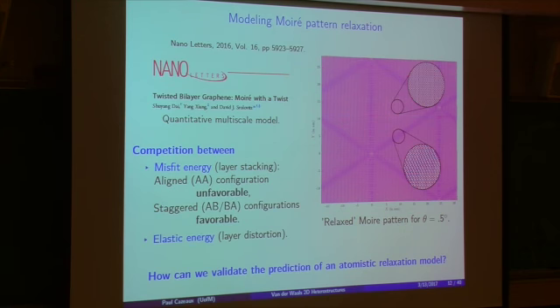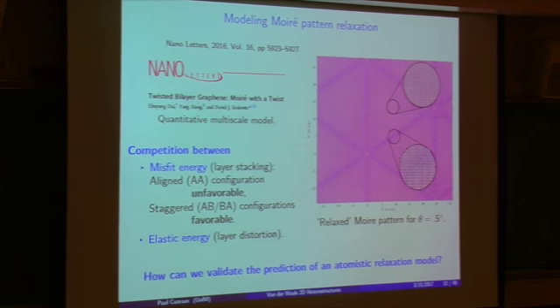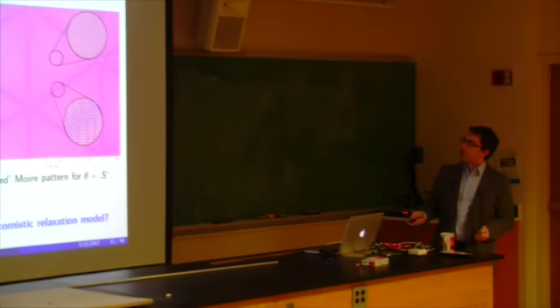And so it will try to relax towards the positions that are preferred. In particular, we have a misfit energy. Some staggering configurations are preferred. If I think about the hexagon on top of the other hexagon, it's better to have one of the atoms sitting in the middle. It's nicer over there than having the two perfectly aligned. So the two perfectly aligned are these AA configurations. They are much more unfavorable compared to nicely staggered configurations like this, where the two lattices are staggered, and they really like this kind of position.